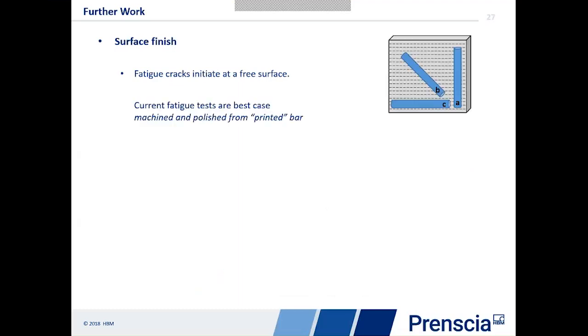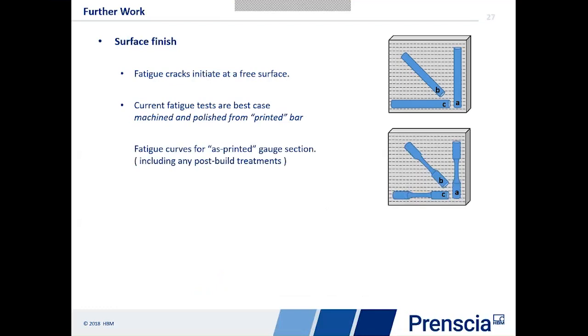The other thing that we want to look at is surface finish as well. We know that fatigue cracks initiate at a free surface. What we've tested right now is that we printed bars and then machined the bars into typical fatigue coupons. What happens if we were to print the coupons themselves? In many cases, when we're looking at additive manufactured components, we're printing surfaces and we can't always polish those surfaces, and we know that fatigue initiates at those surfaces. So what can we do to estimate the effective surface finishes? We're looking here at basically as-printed net section shapes for testing. How do they all compare?